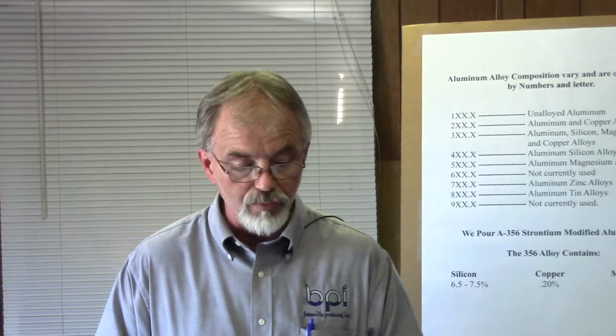For safety reasons, ingots should be preheated before you put them into the melt. Also, if you analyze an ingot, you would find that the elements silicon, copper, and magnesium are stratified. This is because of the slow rate an ingot sets up. Slower setup time means more stratification. Some ingot manufacturers extrude their product. These are not stratified.